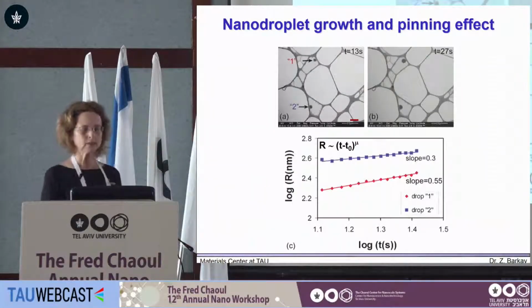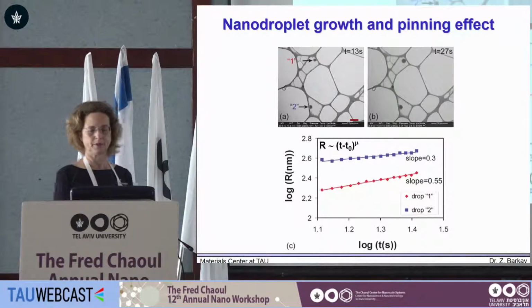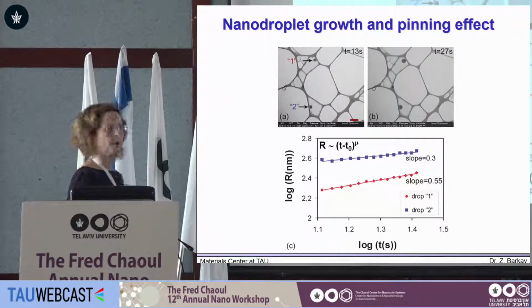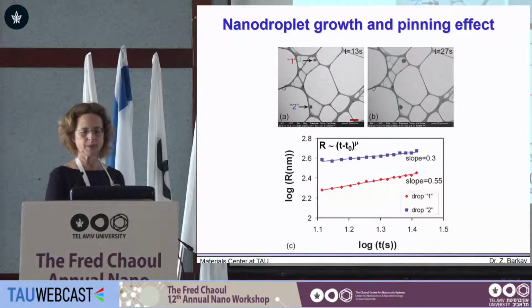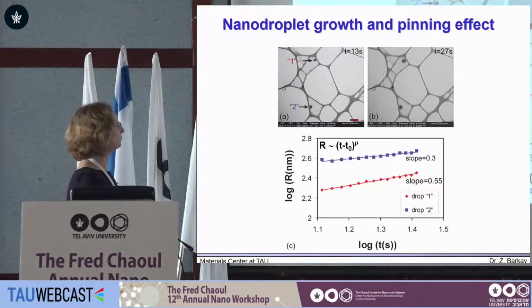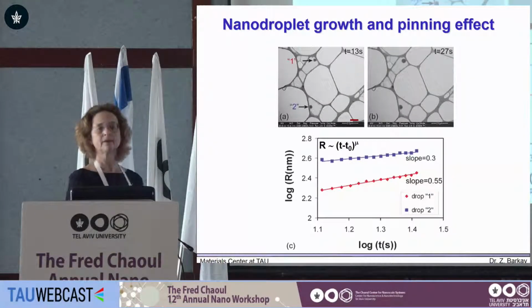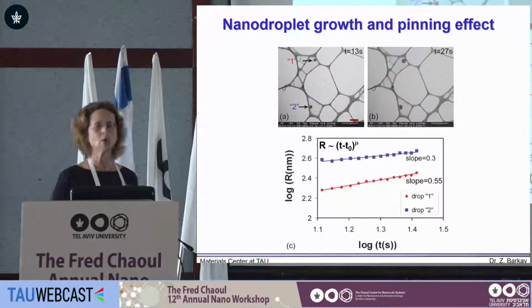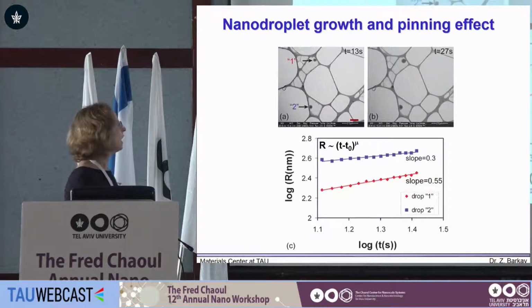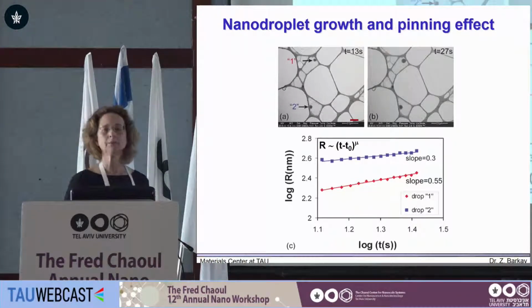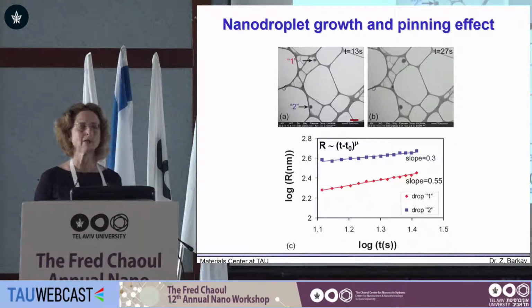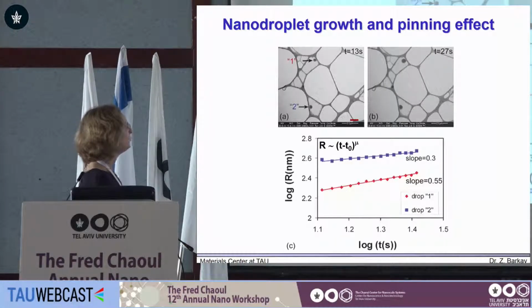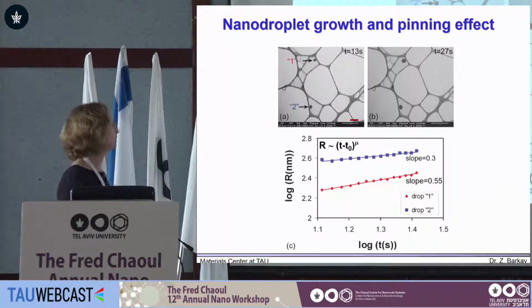So let's look at nanodroplet growth behavior. This is taken from a whole video for growth behavior, and this period of time between 13 to 27 seconds is actually under equilibrium, obtained without changing pressure or temperature in the system. You can refer to two droplets that are attached on the film, at the side of the grid, and we can follow the time dependence of the growth.